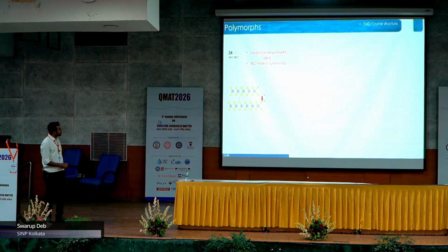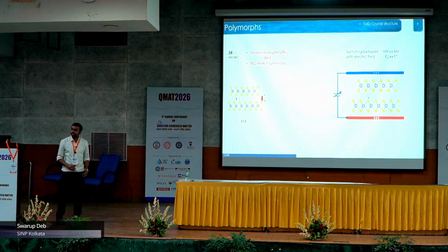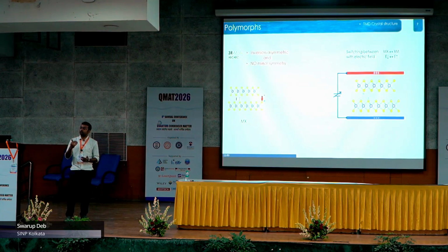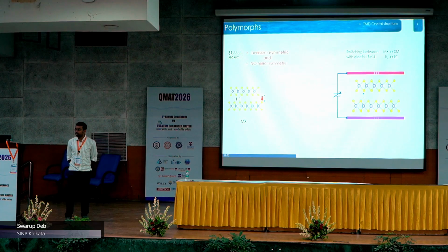So what happens is that when you take this crystal and subject it to an external electric field, like placing it in a parallel plate capacitor, the layers slide with respect to each other. And they slide in a manner that you have once the XM configuration and the other you have the MX configuration. So it is the in-plane sliding of the layers. It is the in-plane degrees of freedom of the layers that gives you a switchability in the out-of-plane direction. And it is this mechanism, the sliding of the layers, that's why it is known as the sliding ferroelectrics.